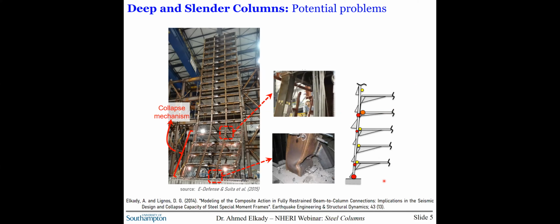As you probably know, moment resisting frames are expected to dissipate the seismic energy through the plastification of beam ends. A plastic hinge can also occur at the first story column base, but other than that, the columns should remain elastic to maintain the structure integrity and the gravity load carrying capacity. Now, of course, this is not always the case. Numerical and shake table tests showed that you can get plastic hinges in columns at higher stories. And this is due to several reasons that are not considered in design. For instance, ignoring the beam strength amplification because of the composite action of the concrete slab can lead to a reverse situation where the column becomes the weaker element in the joint, leading to story mechanisms as the one that you see in this slide.